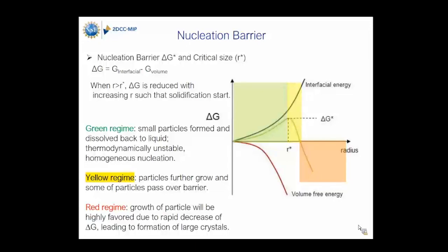But then you wonder, how can I overcome that? How can I pass that barrier? This depends on what solvent you use in solution growth. So selecting an appropriate solvent is critical for solution growth. If the solvent is not the right solvent, that barrier could be high, and it will be difficult to grow crystal. Finding an appropriate solvent, also called flux, is in some cases, especially for growth of new materials, difficult.